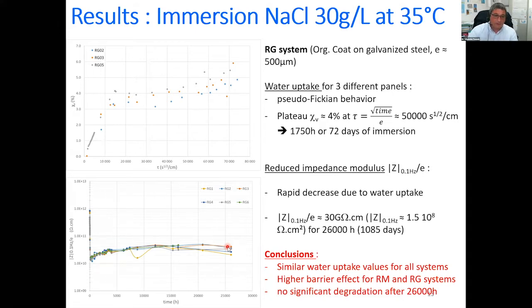So the first thing we can say is that we've got finally similar water uptake value for all the systems. This is not quite surprising because we've got the same paints. They are only applied on two different substrates with a zinc coat or not. So this is okay. We can also observe that we have a higher barrier effect for the RM and RG systems. So maybe a better adhesion of the coatings, but more importantly, we have no significant degradation after 26,000 hours of immersion at 35 degrees C.